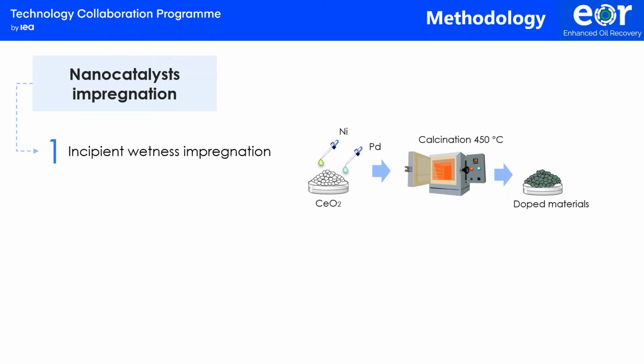On the other hand, the effect of the strong metal support interaction was assessed by doping the different ceria nanoparticles with a couple of nickel and palladium in a mass fraction of 1% of each one.